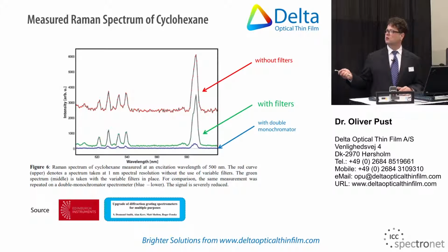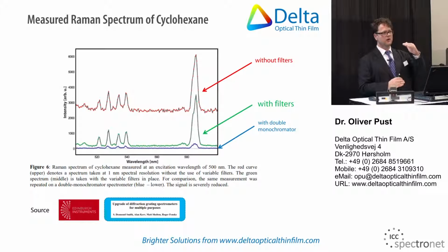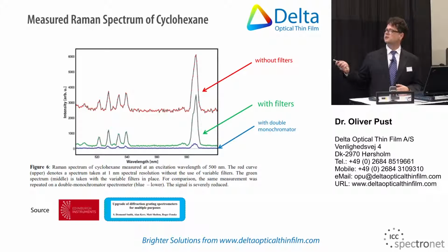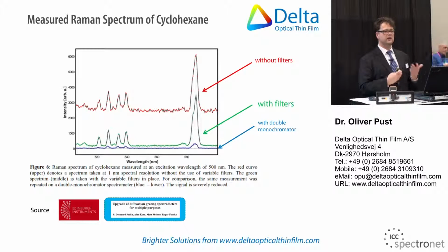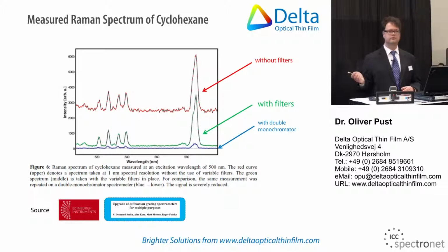Now you take one monochromator and add our tunable bandpass filter. That gives you the green curve. And because of the very high transmission level of our filters, you still have the same signal strength as with one monochromator. But because of the high out-of-band blocking of our filters, you get a noise floor that is on the level with the double monochromator. So that combination gives you the high sensitivity of one monochromator and the signal-to-noise ratio of a double monochromator without being as complicated and expensive as a double monochromator solution.